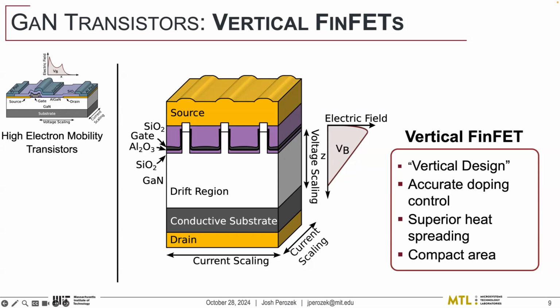Also with gallium nitride, all of these are grown epi layers. So we put it in an MOCVD reactor and we grow this, nanometer by nanometer. And during each of those, while it's growing, we're able to very accurately control the dopants that go within it. So, within a 10 nanometer span, we can go from 10 to the 19 silicon atoms per cubic centimeter to 10 to the 16. We can have very sharp profiles there, which lets us really optimize the electric field and make sure that we're pushing up against that 1D unipolar limit that I talked about. And then there are some other benefits: the heat's generated uniformly, everything's compact, so it switches faster. But those are more second order effects that won't be as important for the rest of this talk.